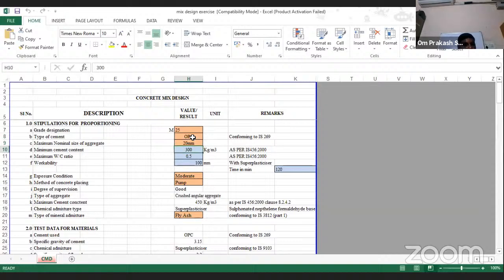According to IS 456, minimum cement content is 300. According to IS 456 table 5, maximum water cement ratio is 0.5. Workability, here I am doing the trial for 100 mm slump. Next, exposure condition, moderate. If we talk about Moradabad or Jaipur, we have moderate conditions. So we are designing for moderate, and according to moderate condition, minimum grade of concrete should be M25. We can design for higher grades, M30, 35, 40. Here we are taking the example of M25.